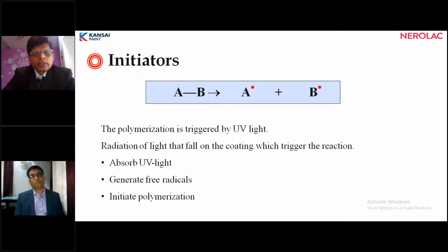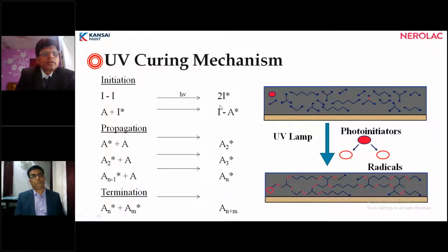Then here, polymerization is triggered by UV light. When radiation falls on the coating, it triggers the reaction: first the photoinitiator absorbs UV light, then it generates free radicals, and then it initiates the polymerization, which we will see on the next slide. You see here initiation, propagation, where the radical form is there, and termination reactions. In the presence of a UV lamp, the photoinitiator initiates the polymerization reaction. It's just like free radical acrylic polymerization.